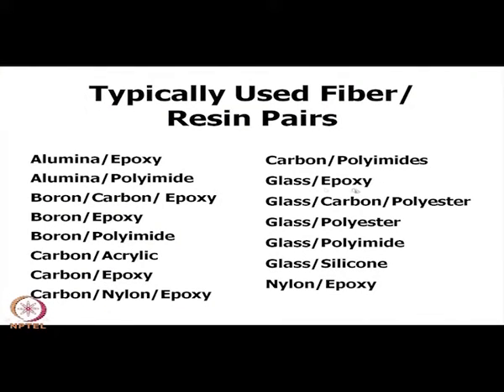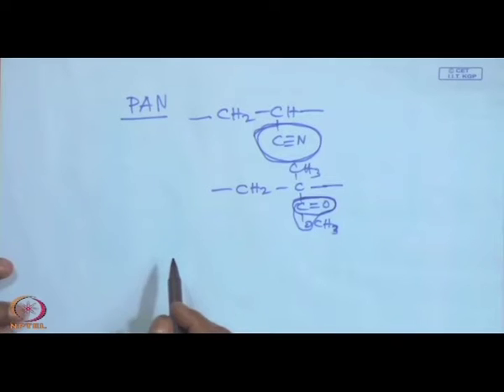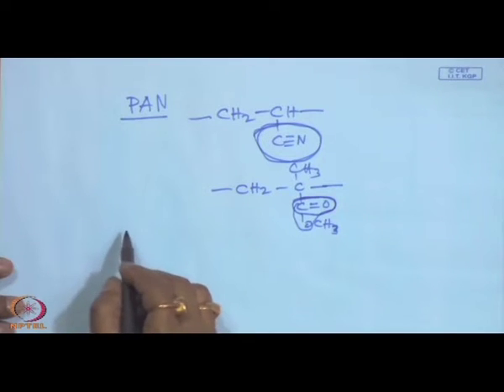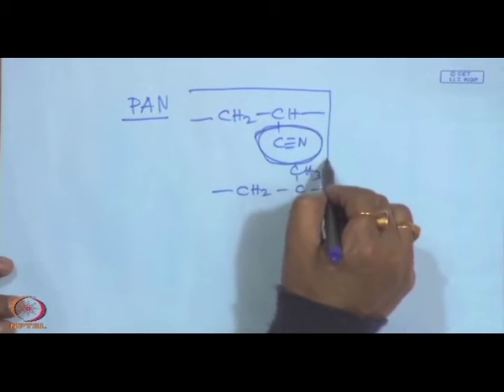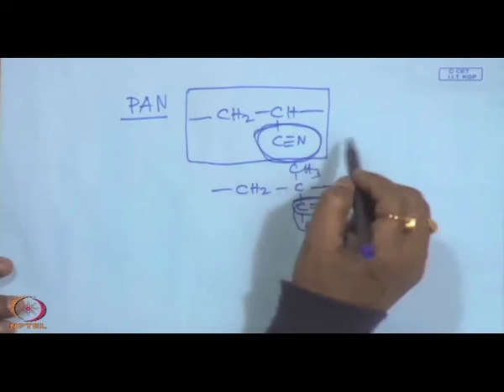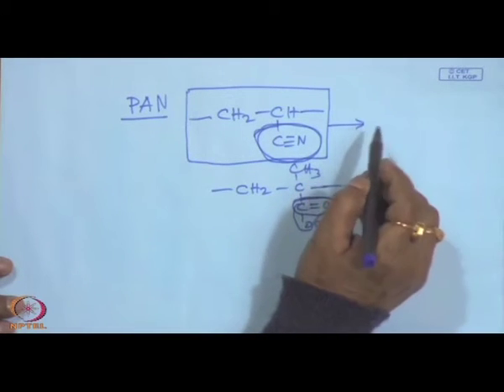So, carbon polyimides, glass epoxy, glass polyester, glass polyimide, glass silicone, nylon epoxy, and carbon acrylic as I was telling, and carbon epoxy, carbon nylon epoxy. Carbon fiber is basically a graphite fiber. A carbon one can have as matrix material or a fiber material. This carbon fiber is made from this PAN precursor. This is the polyacrylonitrile. Now, this polyacrylonitrile precursor is used for making carbon fiber.